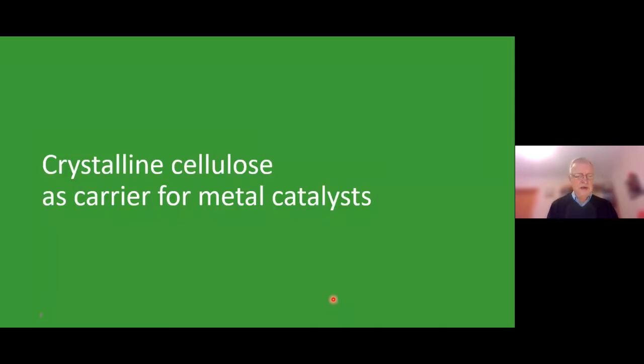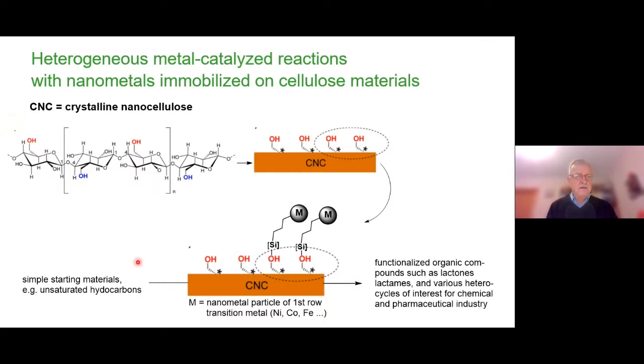Now I will talk about this crystalline cellulose as carrier for catalysts. And here we have crystalline nanocellulose. As you know, we have a lot of hydroxy groups in cellulose. So we use these hydroxy groups exactly in the same way as we use the hydroxy groups in silica. And we can bind now these 3-carbon silyl units to the hydroxy groups. And here we have also bound the metal to the amine, which was here before in this 3-carbon silyl.